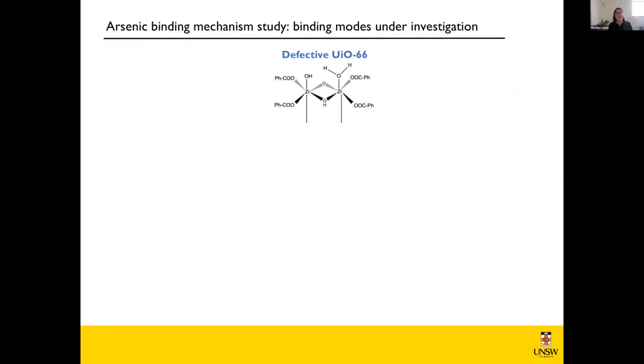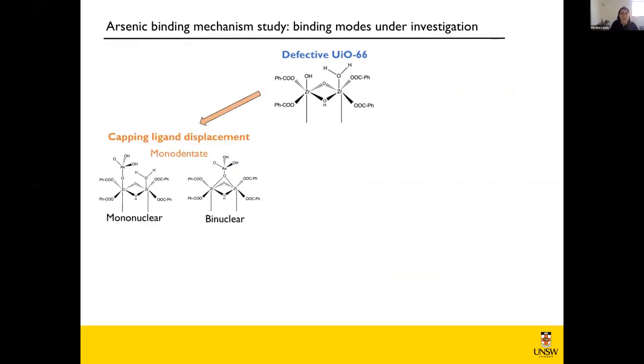So what binding modes are we looking into here for arsenic with this defective UiO-66? We can hypothesize that arsenic might come in and bind in a monodentate fashion, where one of the oxygens interacts with one of the zirconium atoms, or perhaps just one oxygen might interact with both zirconium atoms at once.